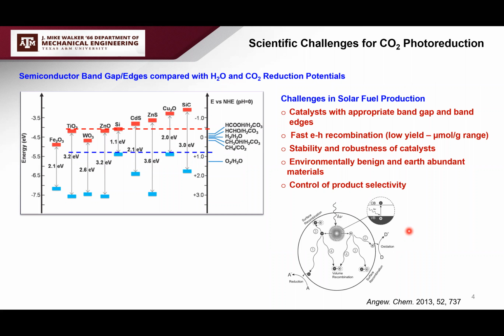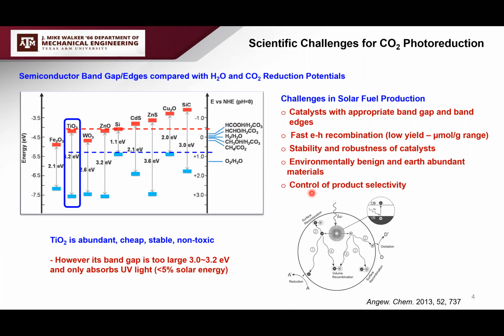Of course, other challenges include instability, toxicity and abundance of the material, and product selectivity. So TiO2 is believed to be very suitable, or I would say widely and extensively studied, because it's abundant, cheap, stable, and non-toxic. But the main drawback is its large band gap, so it only absorbs UV light.